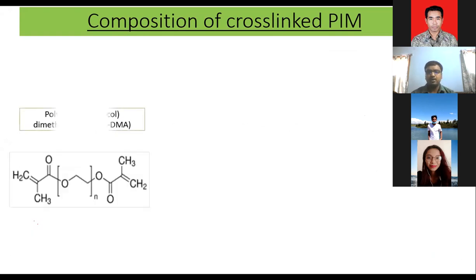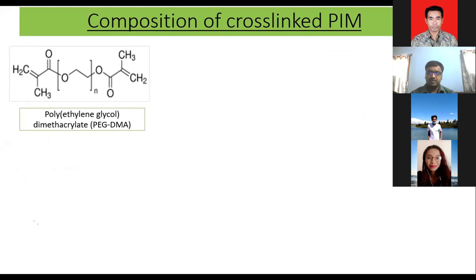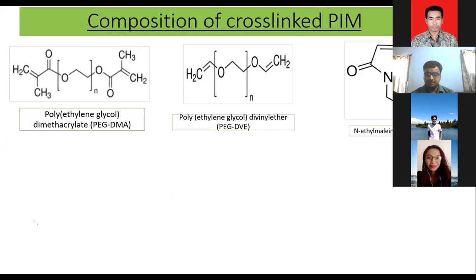As I said in the beginning, my work is on cross-linked polymer inclusion membranes. In a normal polymer inclusion membrane, we have only a base polymer and an extracting agent, and sometimes, as mentioned by Fidel, there is some plasticizer as well. But in a cross-linked polymer inclusion membrane, we use another kind of polymer or oligomer, like polyethylene glycol dimethacrylate. We call this a cross-linking agent. In my study, I have tested three different cross-linking agents: PEG-DMA, polyethylene glycol dimethacrylate, then PEG-DVE, and the other one is N-ethylmaleimide. These are the three cross-linking agents.